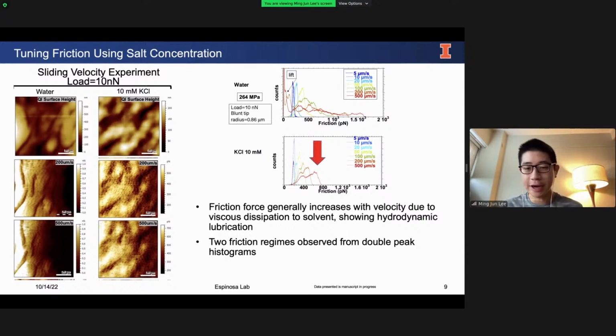And in this arrow here, I'd like to highlight that you can see there are two peaks in the histograms, so two friction regimes. And I'd like to tie this back to the heterogeneous surface structure I showed you in the initial QI images. I had elevated grains that I believe are the copolymer, and then valleys that I believe are the agarose. So I think the copolymer is giving me one range of friction values, and the agarose is giving me a different range of friction values.